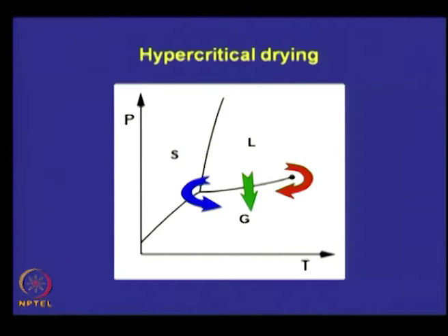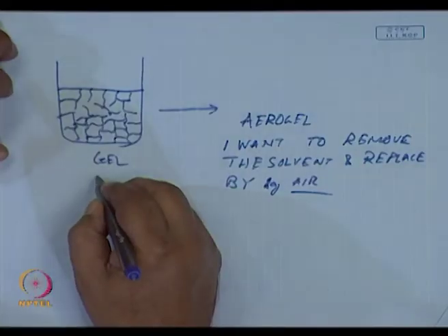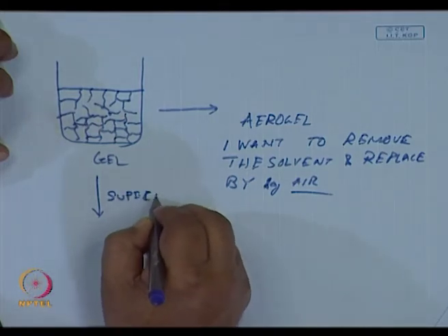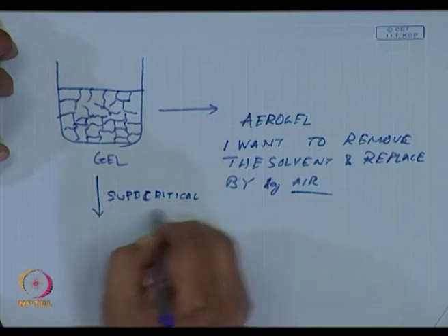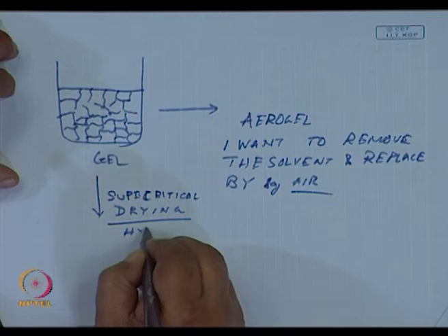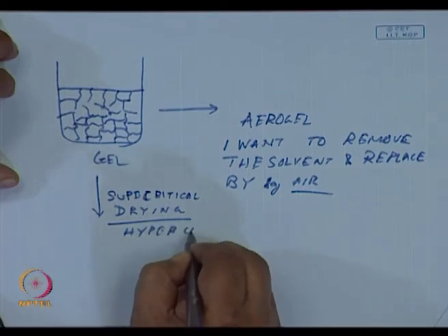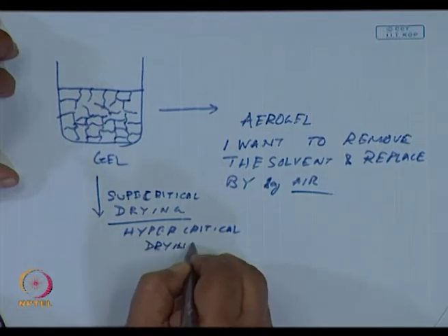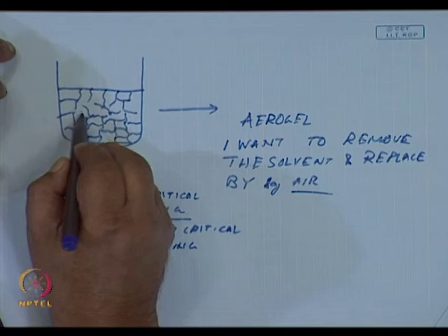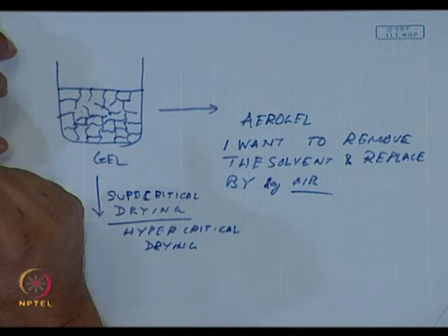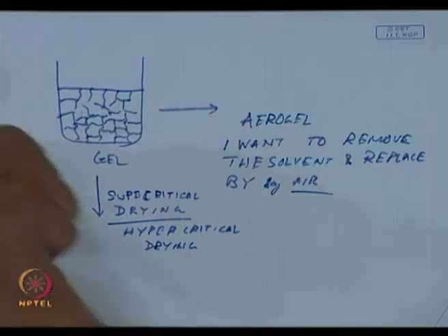So, now if I take this gel and subject it to supercritical drying, or hypercritical drying, all the solvent in these spaces would no longer remain a liquid, but would be converted to a gas.